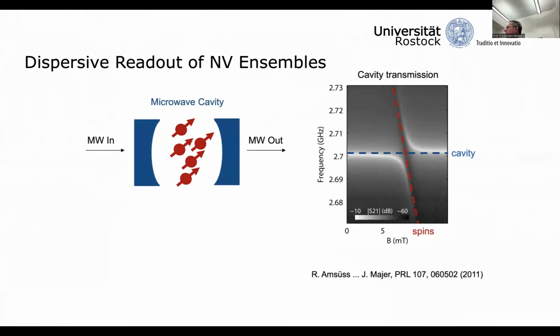When we embed NV centers into a microwave cavity, we essentially can use them as a real circuit element. We can send a microwave signal through such a cavity, and this microwave signal can directly couple to the electronic ground state spin transition, because this is the spin transition in the microwave range. When we do this with a large ensemble, one can even reach the strong coupling regime, where the cavity resonance is split into a pair of cavity polaritons by coupling to the NV centers. And intriguingly, this can be used to implement readout of the spin state.